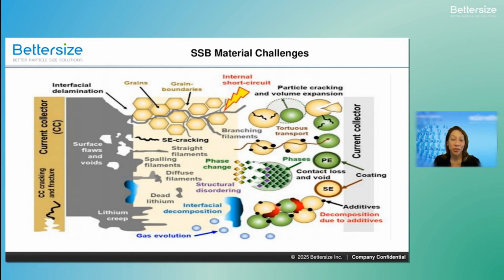There are major issues, including the limits of solid electrolytes, which have low ionic conductivity at room temperature versus liquid electrolytes. There's grain boundary resistance in ceramic electrolytes, which reduces overall performance. There's moisture sensitivity, especially for sulfide-based electrolytes, which makes handling and processing difficult.